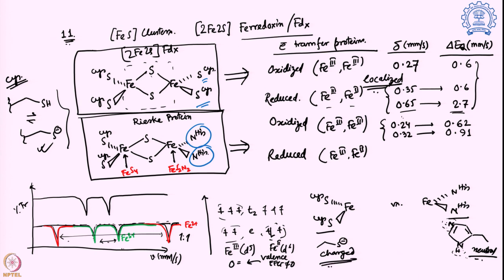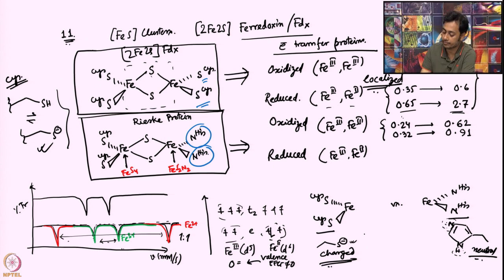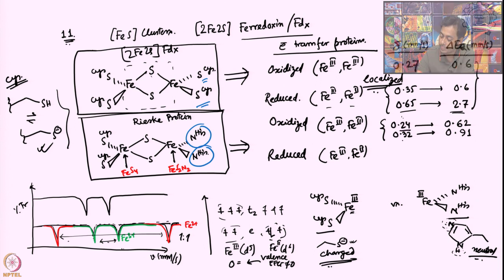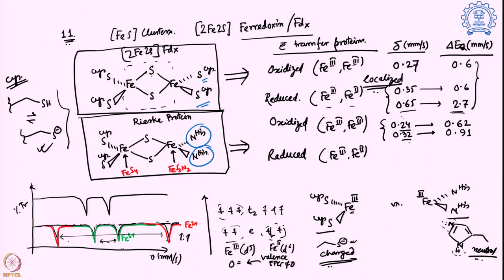So now the charged system versus neutral, which one of them is going to stabilize an oxidized iron system? The charged one, through this ion-ion interaction. So that is why over here the iron 3 plus will be more prominent compared to this iron 3 plus over histidine. That will be much more charged, and the slight difference in the charge will showcase over here. So one of them is 0.24, one of them is 0.32.